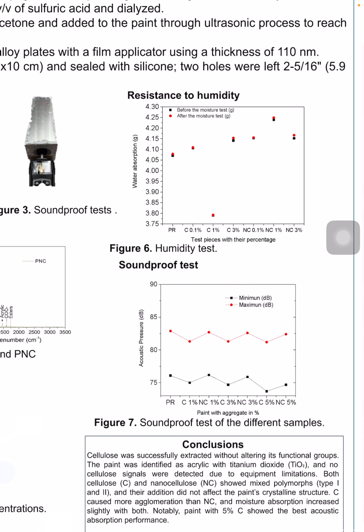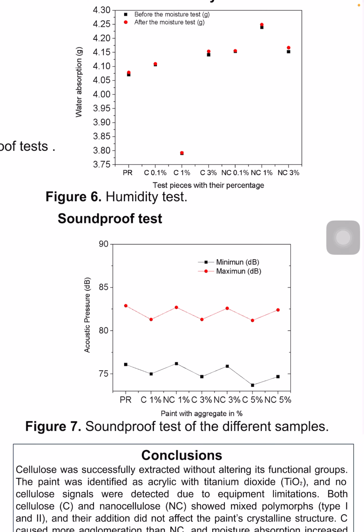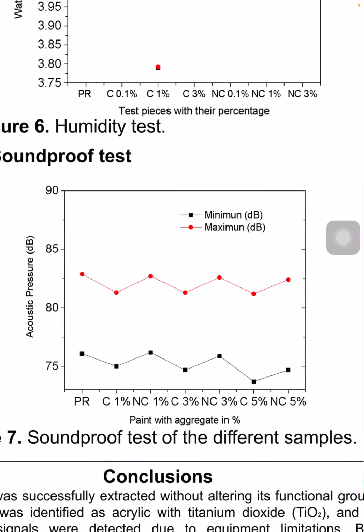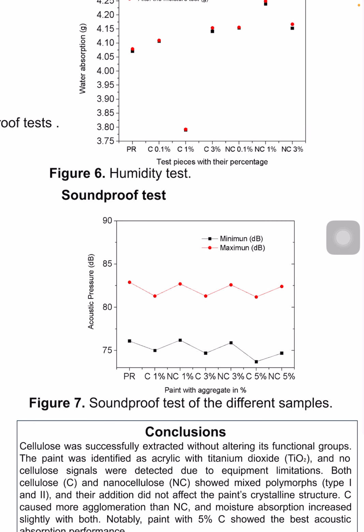And in the soundproof test, we can see that C at 5% has the lowest acoustic pressure. It seems like the acoustic pressure goes down. So in this case, the 5% is our best soundproof performance.